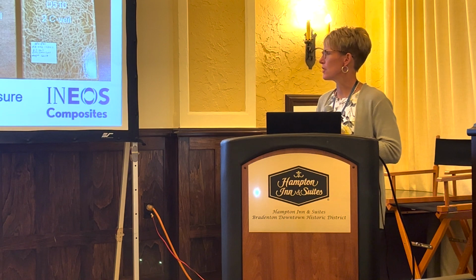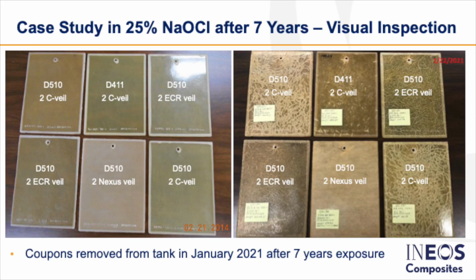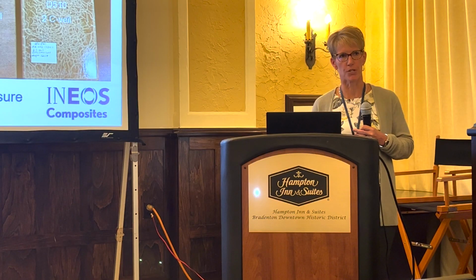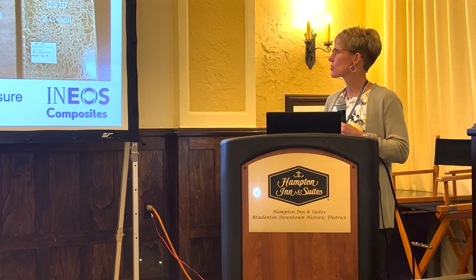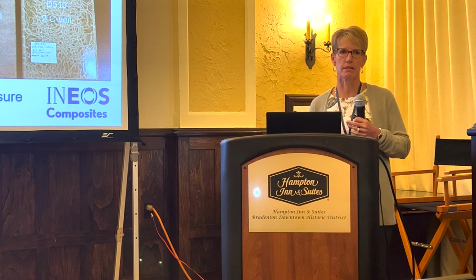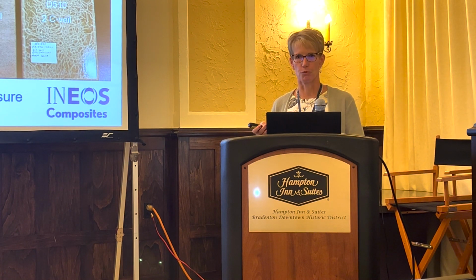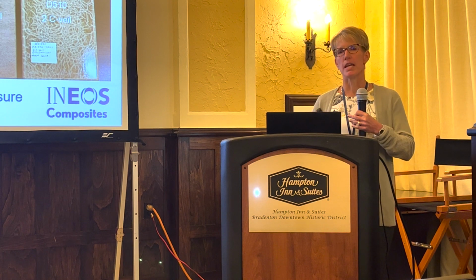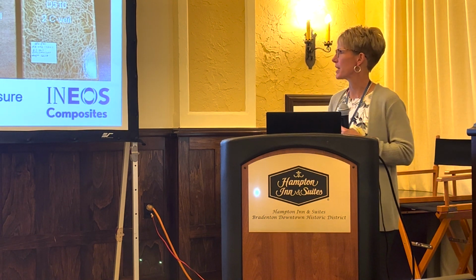They were removed in January of 2021 after 7 years of exposure. We did see, as you can see, some cracking. As Mike mentioned earlier yesterday, this cracking was really only on the surface, and it was determined that it was due to thermal cycling, where they were introducing cold sodium hypochlorite into a warmer tank. So we did see this cracking, but it did not affect the integrity of the resin. Once it formed, it didn't progress over the years, and it was really only in that veil layer.